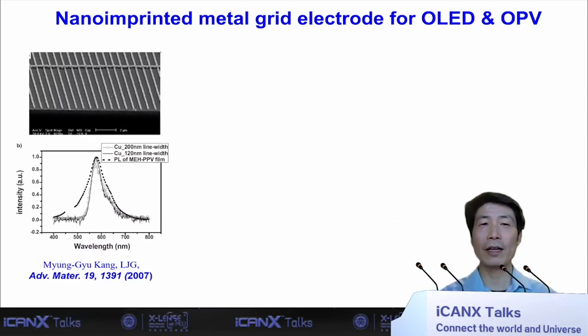Traditionally, people have been using a material called ITO, indium tin oxide. It's a conducting oxide material. So back in 2007, we did a first demonstration of making a metal grid by using nanoimprint. We made, in this case, an organic light emitting device out of this structure.